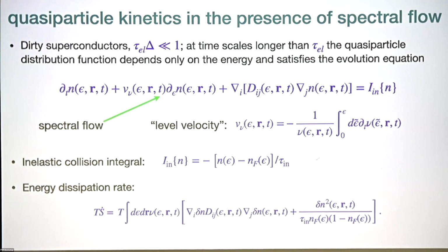What they do have is this spectral flow term, and this coefficient here is expressed in terms of some spectral current. It has a more complicated form in terms of Green's functions, but you can show that for small gradients, the expression reduces to this very simple local dependence. So this is a rather general scheme which describes non-equilibrium superconductors at small spatial gradients. And then to find dissipation, you just have to add the expression for the entropy production rate. It arises from diffusion and from inelastic collisions.